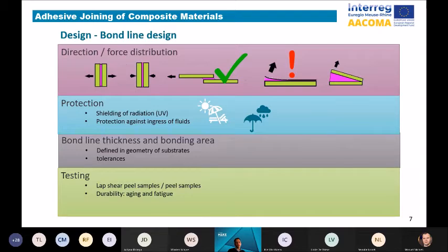Simultaneously with the adhesive selection, you have to design the bond line. Please design the bond line to absorb tensile, compression or shear forces and avoid peel forces. These peel forces cause very high peak forces, and this joint cannot withstand them. And in a good design, you prevent exposure of the bond to UV or ingress of water and chemicals. Preventing this will lower the influence of aging and thus enlarge the lifetime. The design of the bond line depends on the type of substrates, adhesives and the type of application. A thin bond line is used for rigid structural joints, and a thicker bond line can absorb movements and can also absorb tolerances in the substrates, in the composites.